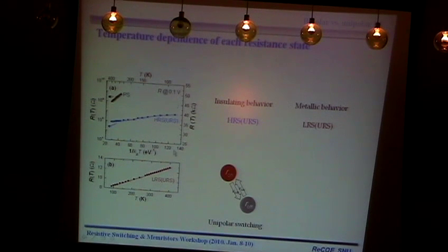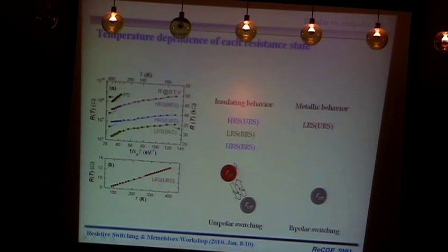So in order to describe this one, we need two things. One is a metallic, and the other insulating, and the switching between those two, we can describe the changes between this state, which was already demonstrated earlier. On the other hand, if you look at the bipolar resistance state, both of the low resistance state and high resistance state are insulating. This indicates that this insulating state should be interpreted with two new insulating states.